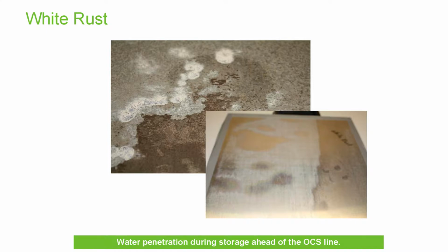They're manifestations of problems in that upstream process, whether at the rolling stage, which are more related to mechanical properties, where you begin to get scratches or surface contamination, particularly from the galvanizing process. Then you get into physical areas where the transfer between the upstream supply chain and the coil coating line is not perfect. The coils get knocked when they're on cranes. They get put in sheds that leak. All of this complicates the quality problems that the coil coating line has, because as David will explain in a moment, there's enough issues around how you get the paint on properly and making sure that paint looks the right way without having to bother with these kind of defects.